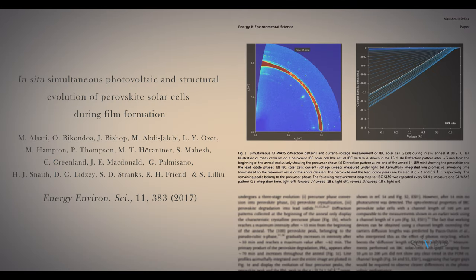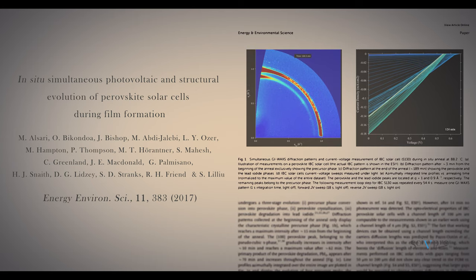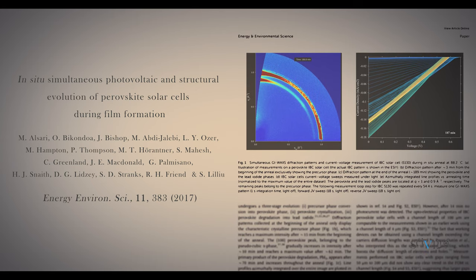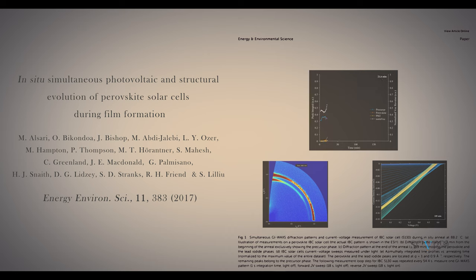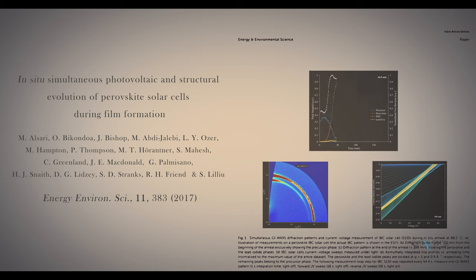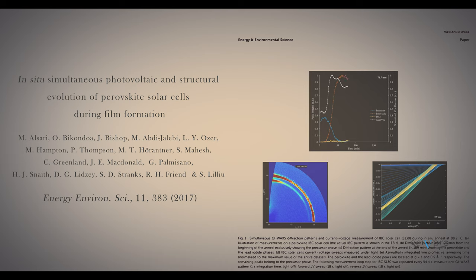And we used these structures to investigate the relationship between the structural properties and the device performance of perovskite solar cells during film formation, during the perovskite formation. So, we found that the precursor phase displays clean semiconducting behavior. And we also saw that the VOC peaks before the precursor fully converts into perovskite.